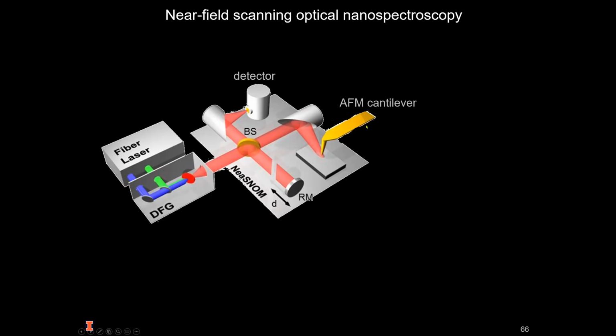The enhanced electric field caused by the tip in the near field will cause a stronger emission by the sample, which can be measured in the far field. This emission will be still much smaller than the scattered light in the far field by the sample. But using phase-sensitive detection, we can separate the near field signal from the far field background.